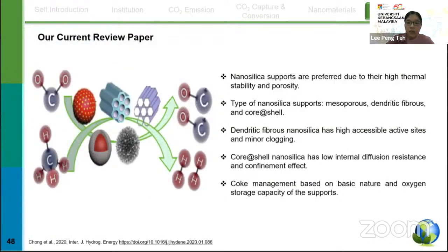I would like to draw your attention to our recent review paper published about nanosilica materials for syngas production via CO2 reforming of methane. We highlight that nanosilica supports are preferred due to their high thermal stability and porosity. Then we have different types of nanosilica support discussed in this review paper, for example mesoporous, dendritic fibrous, and core-shell. Dendritic fibrous nanosilica has highly accessible active sites, so it leads to minor blocking of the materials. While core-shell nanosilica has very low internal diffusion resistance and also a confinement effect. For dry reforming of methane, coke management is very important. This can be managed by the basic nature and also the oxygen storage capacity of the support.